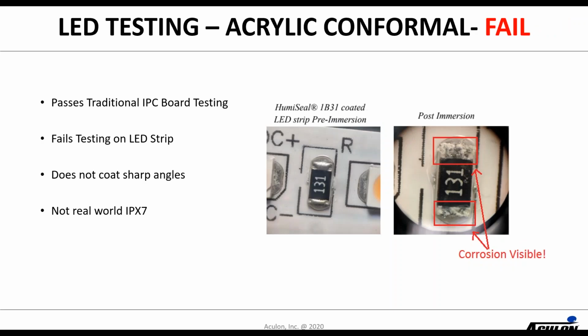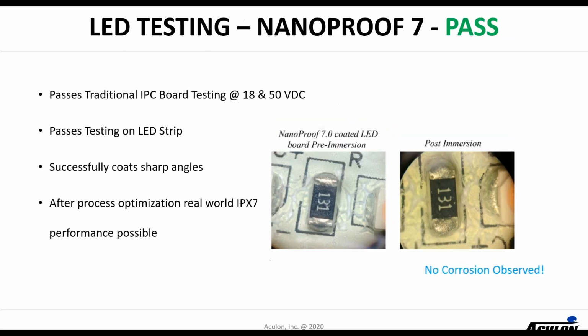And you can see the exact same thing here with the traditional acrylic conformal coating. Again, they slumped down, they only coated the top of the component and then slumped down into the flat areas, left the edges unprotected, and you get a failure. Alternatively, with the tricks that we've utilized in our more advanced nanoproof coatings, such as nanoproof 7, 8 series, 2 series, and 12 series, we've specifically developed them so that they actually do conform to the sharp angles. So not only do you get protection on a flat IPC board, but you also get protection on your real world 3-dimensional components.